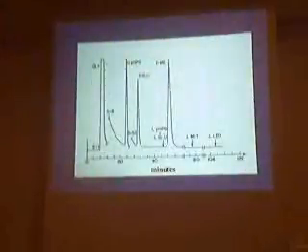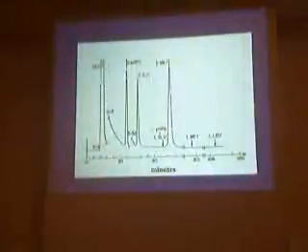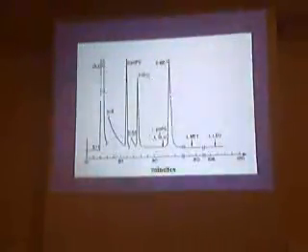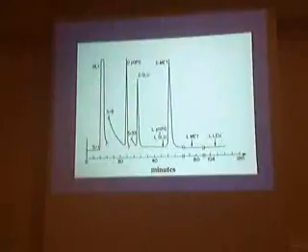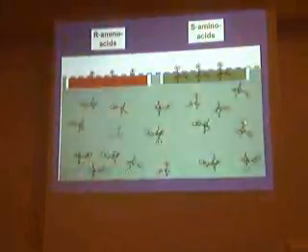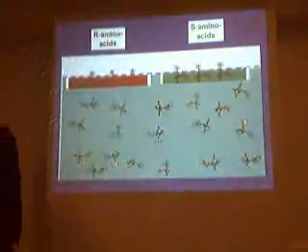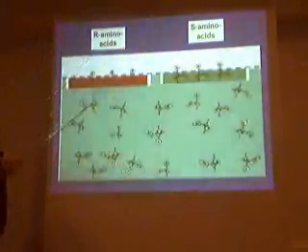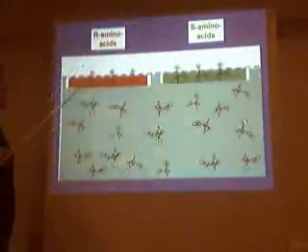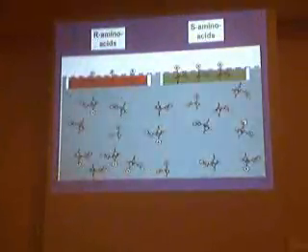Well, this is again the HPLC. If you analyze these crystals, you could see that some of them contained the DL, like it was in this case. So what we suggested at this particular time was that if we are adding L-leucine to the solution, we might have formation of a cluster where the polar head groups of this cluster constitute the first layer of glycine.